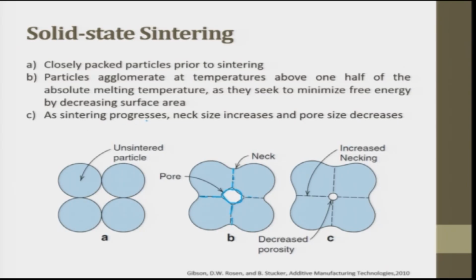So, as the sintering process progresses, the necking size increases and the pore size decreases. So, it is very clear how sintering progresses. What is sintering? It is temperature and time, a combination of this. So, you can try to reduce the pore size and increase the necking area.